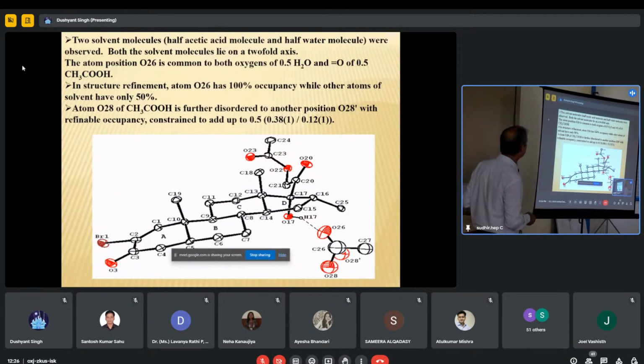Then the idea came, it may be a half water solvent. When we did that, the R factor drastically came down. Otherwise, your R factor will be stuck at 10%, 11%. You are unable to get down to 4-5%.